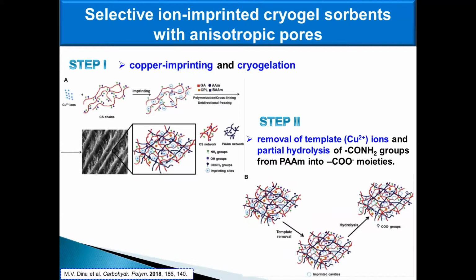In our group, we designed selective ion-imprinted cryogel composites with anisotropic structure by a strategy which combines ion imprinting and unidirectional freezing in liquid nitrogen. In the first step, copper-imprinted interpenetrating polymer networks were prepared by simultaneous cross-linking of copper chitosan complexes by glutaraldehyde and polymerization of acrylamide in the presence of bisacrylamide using the unidirectional freezing methodology. In the second step, the removal of copper ions by EDTA generated well-defined 3D cavities.